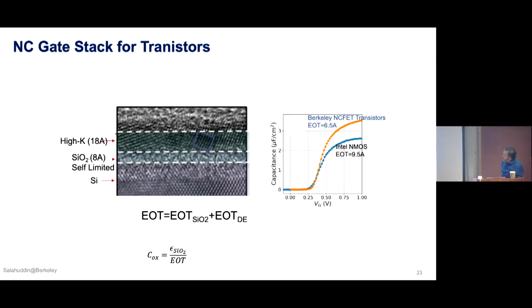So now with that understanding, we can look at some of the gate stacks that we have made, the gate oxides here at Berkeley. So this is a silicon substrate. And then what we have is SiO2. We need this SiO2 in silicon transistors to make sure that the electron transport property in the silicon is not affected. And typically there is a way to do this. This is called a chemical growth, which is self-limited. So it actually gives around 8 angstrom silicon dioxide for everybody. Even in our advanced transistors, the same process is used, and it is around 8 angstrom.